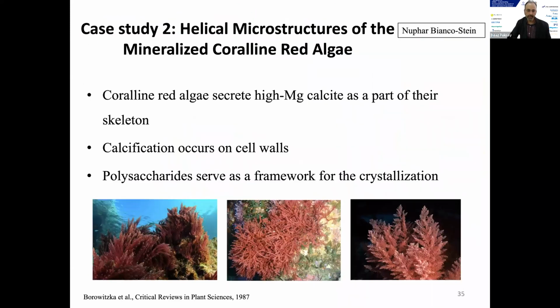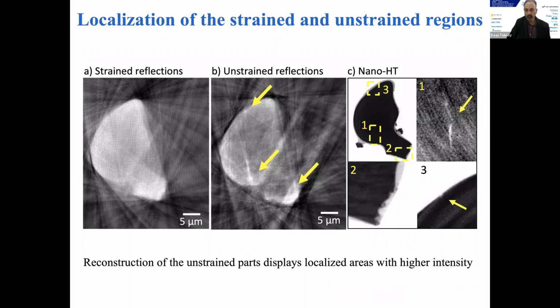Yeah, so that's an excellent question, and of course we always have to make sure whether the diffraction peak position is due to magnesium or strain. So I didn't mention it, but we actually have in this system, at least, an internal standard, and we're quite lucky to have that. I mean, we have this debris that you can see here on the surface, and this actually comes from another lens that we broke. I didn't show it, but we can actually show that when you look at the lattice parameters that are coming from this debris that is already broken, we actually have the same lattice parameters as those of powdered samples.